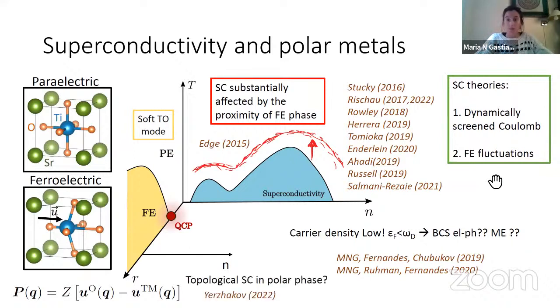And then I think something also very interesting that has not been explored too much, that maybe goes even beyond what the mechanism is here, is that when you dope the system and you start from the ferroelectric phase, so you start adding carriers, then you're in a polar metal. That means that your inversion is broken, you have a polar axis, and now it becomes superconducting. And I think it was last week, there was this arXiv paper claiming that you may have topological superconductivity in this kind of situation. You have all the classic ingredients: spin-orbit coupling, inversion symmetry breaking, and superconductivity. So I think this is also a very interesting thing to think about.